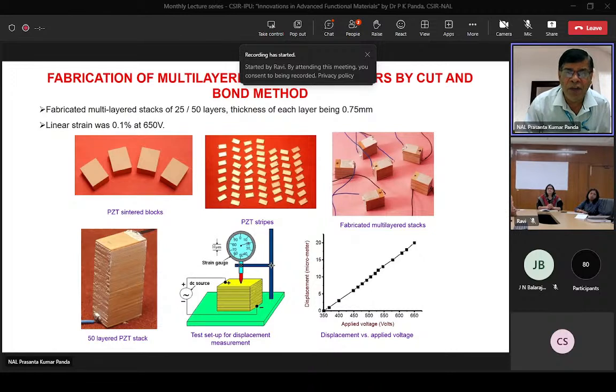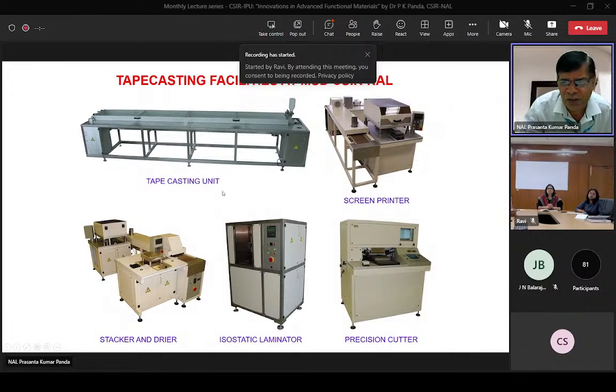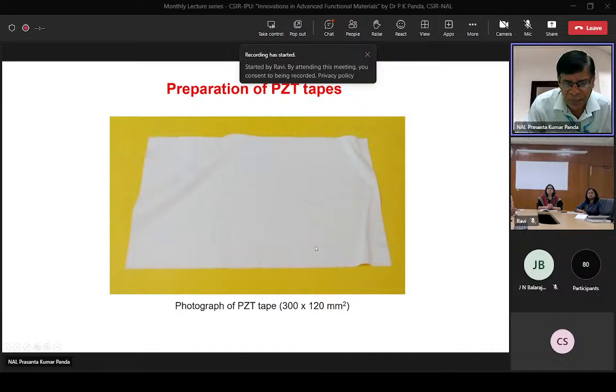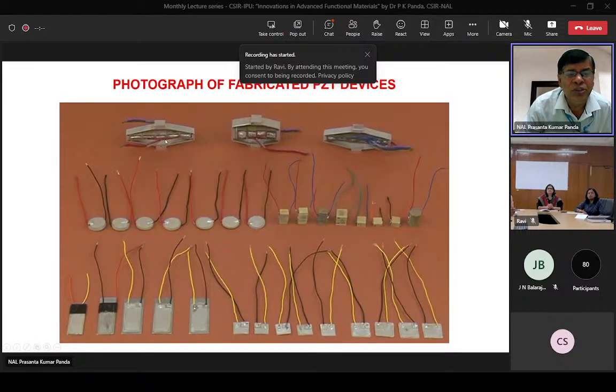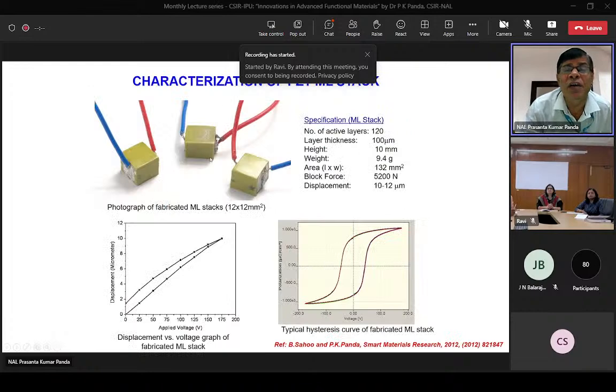When this was developed, there was a brainstorming discussion that we have to reduce further, because this was still requiring 650 volts. Then we calculated that each layer must come down to 100 micron thickness. So we had to get a tape casting unit, screen printer, and precision units. They were purchased from Slovenia under a 5-year plan project. As you can see, this is a photograph of a typical PZT tape. Using that, we have developed amplified actuators and various other multilayered stacks. Typically, here there are 120 layers, each layer is 100 micron, the weight is 9.4 gram, and the area is 12 mm by 11 mm, which is 132 mm square.